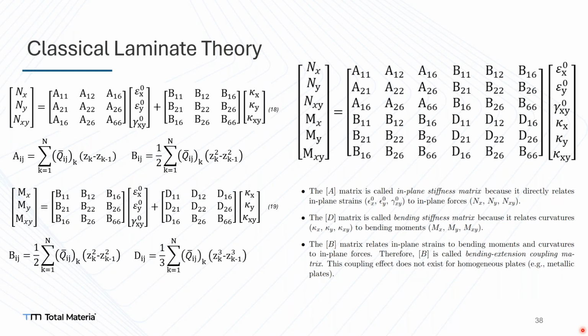Yeah, ABD. From that we will get a matrix called the ABD matrix. It is a really important matrix because it tells us the behavior of the composite. The A matrix tells us the in-plane stiffness of the structure, so it's the basic in-plane properties. The D matrix, called the bending stiffness matrix, relates the bending moments. And the B matrix relates the in-plane strains to bending moments and curvature. So it is a bending-extension coupling matrix.